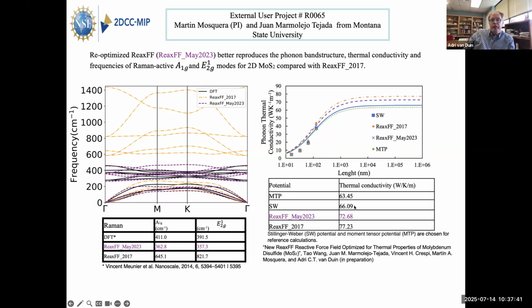And how fast these hotspots resolve themselves can be very important for material growth. Our new force fields actually do pretty well for thermal conductivity compared to the Stillinger-Weber potential, which is very good in that particular area, and also to machine learning-based potentials.